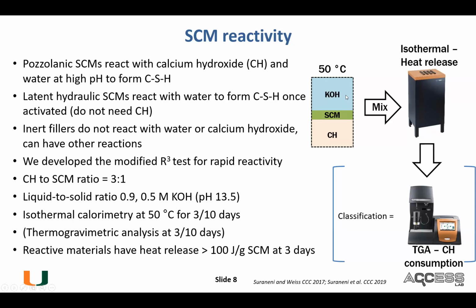So this test is really very simple. You take calcium hydroxide to SCMs in a 3:1 ratio. You put in a 0.9 liquid to solid ratio. You have half a molar of potassium hydroxide. And then you run isothermal calorimetry, which is just a measure of heat release, at 50 C for 3 or 10 days. Optionally, if you want to measure the amount of calcium hydroxide that's consumed in the reaction, you can run a thermogravimetric analysis at 3 or 10 days.